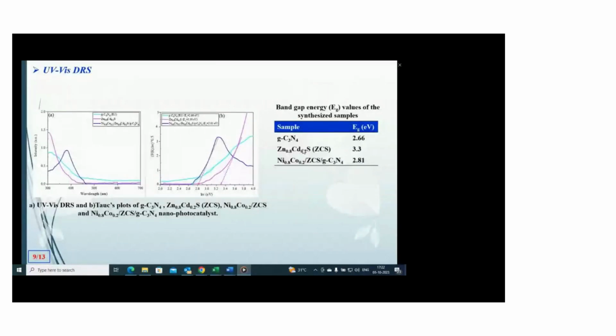This figure shows the UV-visible DRS and Tauc plots of the synthesized samples. According to figure A, the ternary nanophotocatalyst shows a higher absorbance compared to g-C3N4 and ZnCdS between approximately 355 nanometers and 537 nanometers. And this effect can be attributed to the formation of a direct Z-scheme configuration between NiCo, ZnCdS, and graphitic carbon nitride. And this structure effectively suppresses electron-hole recombination and prolongs their lifetime.